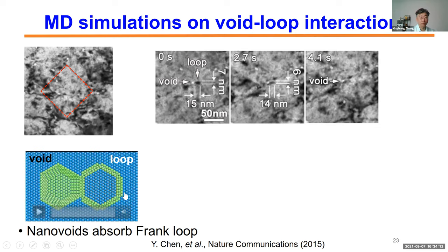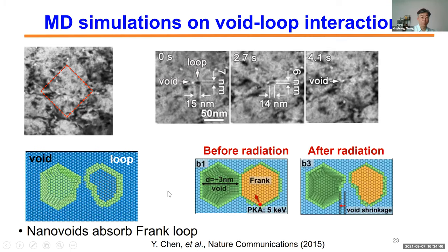And this is an MD simulation performed by Jian Wang, where he put a nano void, but he sectioned it open, so you can see the inside of the void. And he also put a Frank loop, which is an interstitial loop, right next to it, hexagonal shape. And during radiation, what you find out is, and this is copper self-irradiation, all these interstitials, many of them swim into the void as if this is a swimming pool. The interstitials generated during radiation move into the void. And when that happens, you naturally partially fill in the void and partially destroy the loop. Consequently, what the nano void is going to do is absorb radiation-induced interstitial loops as well as introduce the void shrinkage phenomenon. So this is what we find from experiments and simulation.